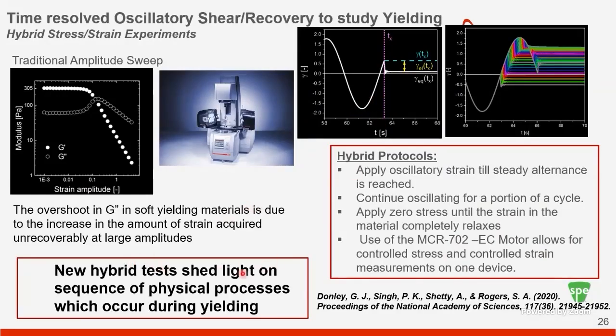And these new hybrid tests really shed light on the sequence of physical processes which actually happen during yielding. Simon's group has taken it much further, and they've done a lot of work on this. And please check out the recent articles published by the group where they have used this hybrid stress strain protocol to really uncover underlying material physics, which is traditionally not possible if you just do an amplitude sweep.